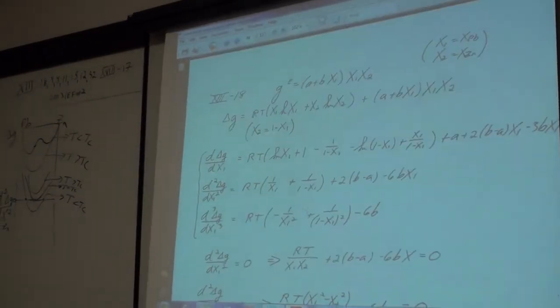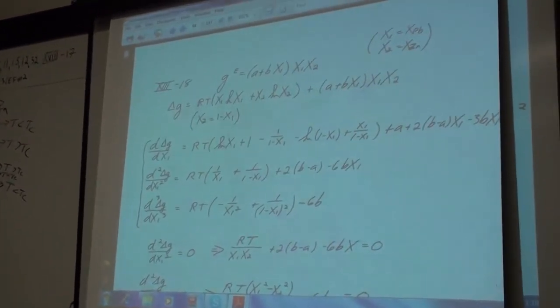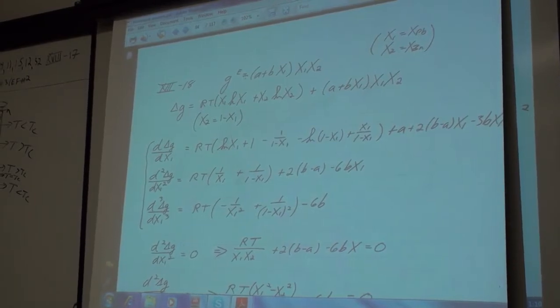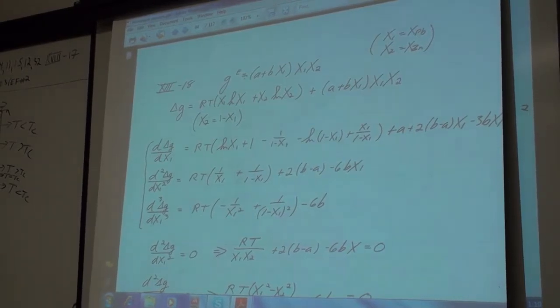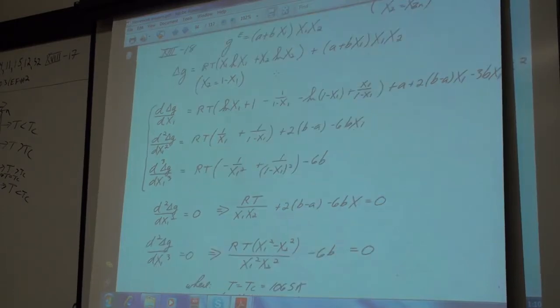So in this case, X2 was zinc. So the A parameter should be positive. The B parameter should also be positive. No, the B parameter is negative. How do we get that? Oh, B X1, okay. So in other words, this GXS is positive everywhere, but it's even more positive as you go towards the zinc. So if this is B times X lead, the B will be a negative term. Any questions about that? So the B is the asymmetry term, and the A is A minus B X1. A plus B X1 is the overall GXS term.